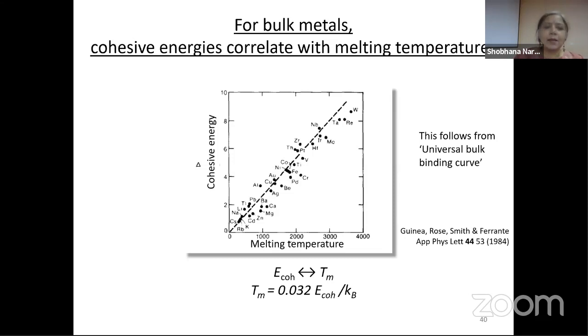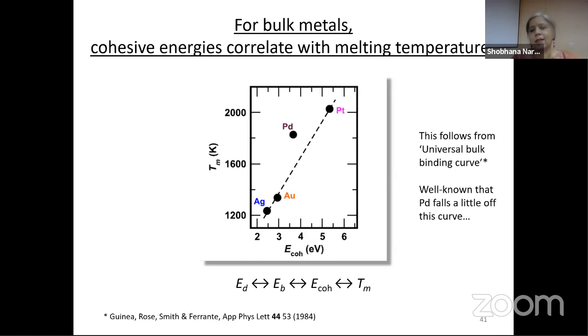Okay, now for the bulk metals, it's a well-known result in the field of condensed matter that the cohesive energies correlate with the melting temperatures of the bulk. This follows from something called the universal bulk binding curve. So this shows this correlation. But incidentally, it is also a well-known result that palladium falls slightly off this curve. So I've shown you that the diffusion barriers correlate with the binding energies. The binding energies correlate with the cohesive energies, and the cohesive energies correlate with the melting temperatures. And so the diffusion barriers correlate with the melting temperatures, which is what I wanted to show. So I hope I've shown you that this is a reasonable argument.